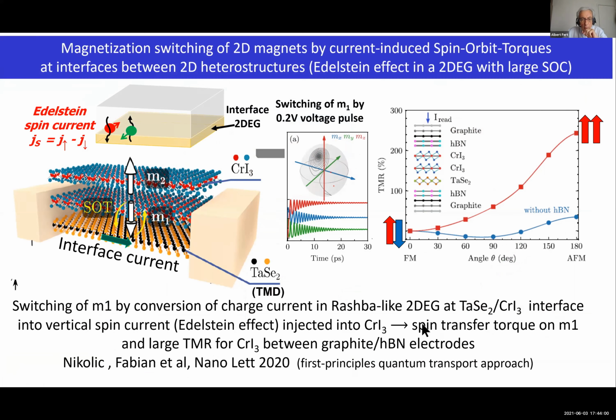So I realize that I confused something in the preceding slides. In fact, because spin orbit coupling is important in the 2D materials, it should be possible to use spin orbit effects in the 2D materials also, and especially at the interface, because the most interesting physics is at the interface. And this is an interesting theoretical result showing how the spin orbit coupling at the interface of a 2D material can be exploited. This is a theoretical work based on a first principle quantum transport approach by a group which is expert in this type of modeling of the transport properties.